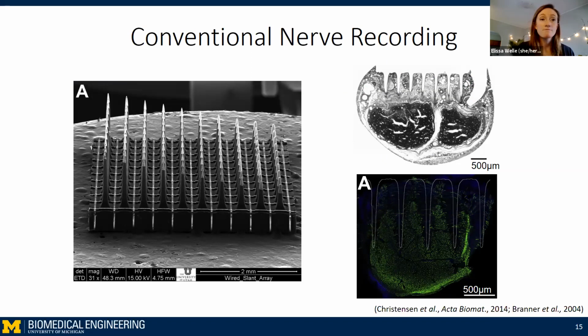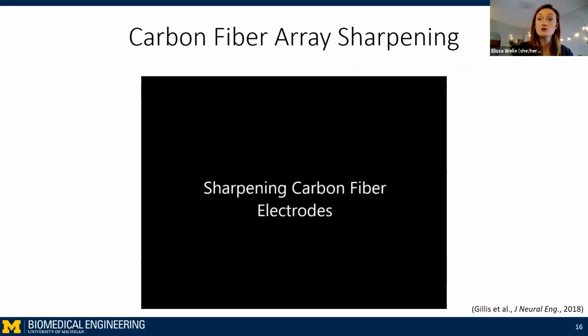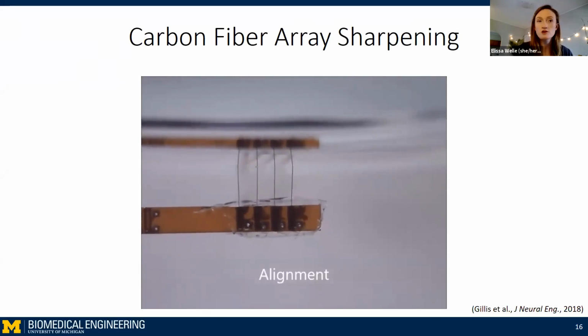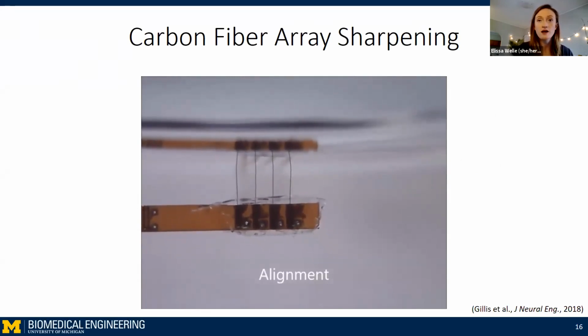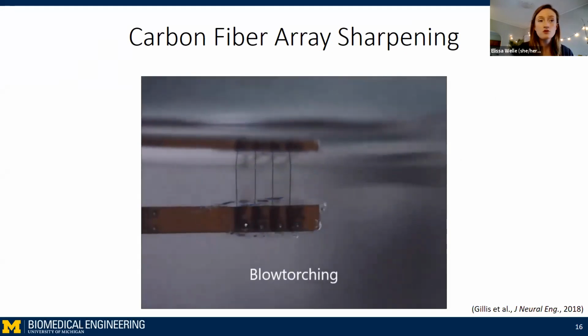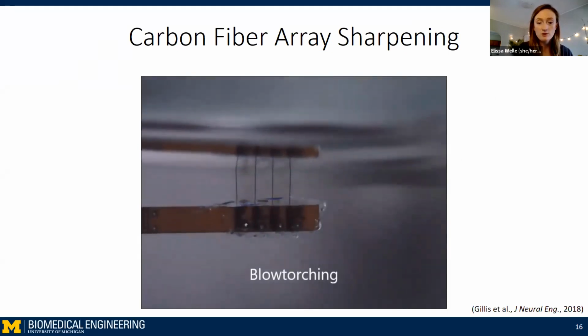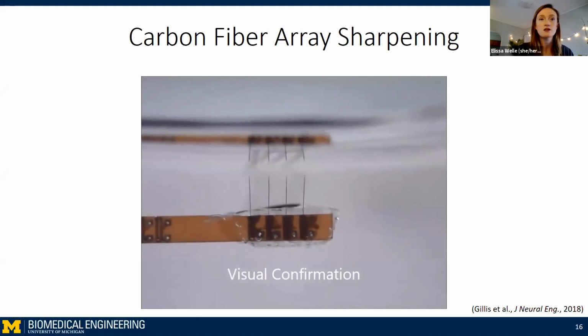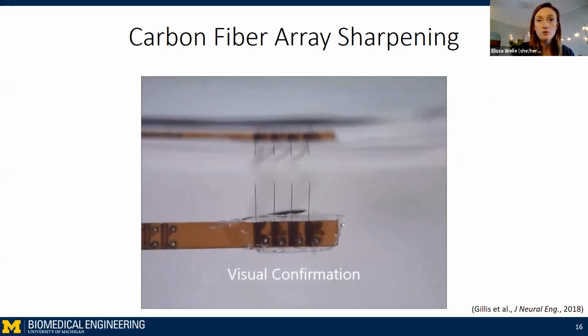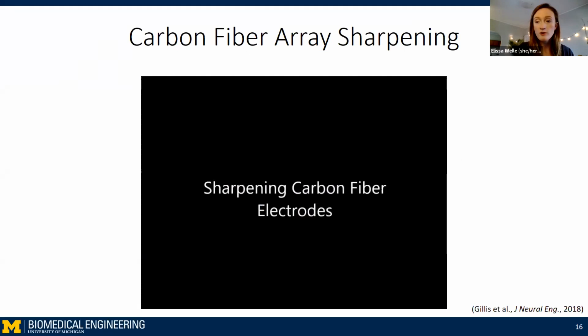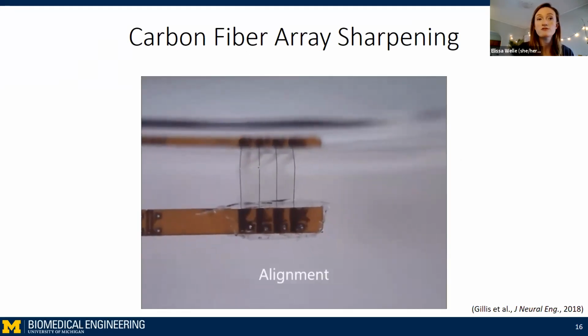So the natural next step is to apply our carbon fiber technology to the peripheral nervous system. In that process, the first challenge was to be able to actually insert these 8 micron fibers into a nerve. We took inspiration from methods used by the Gardner lab and sharpened the fibers. The trick here is all about visualization. I'm going to play this video again so you can see it twice. We submerged the array underwater in a water bath. The water bath acts as a flame retardant, and we're sharpening them with a small butane flame.